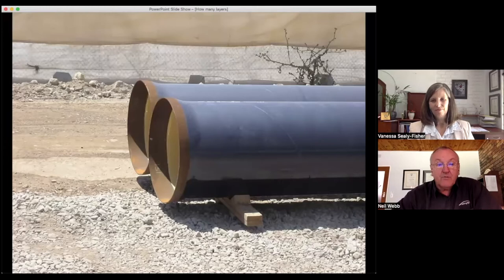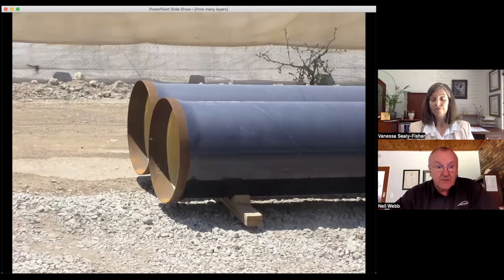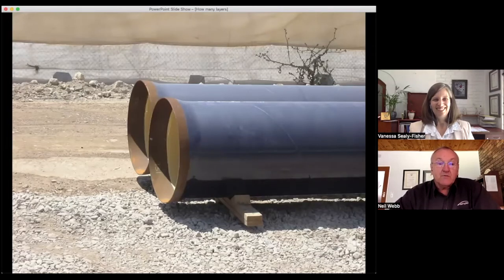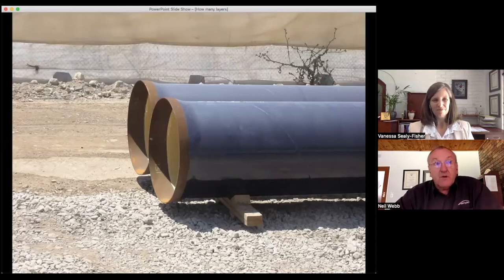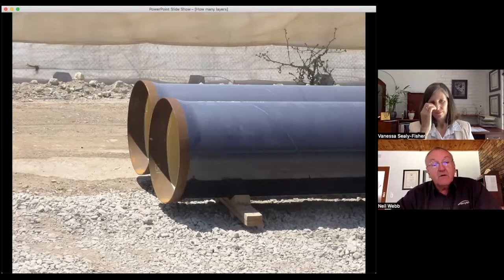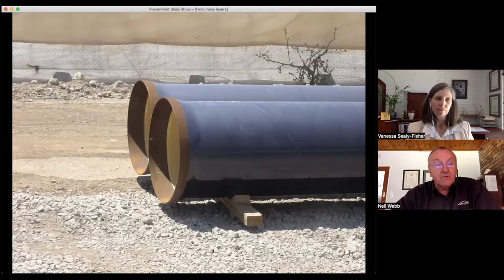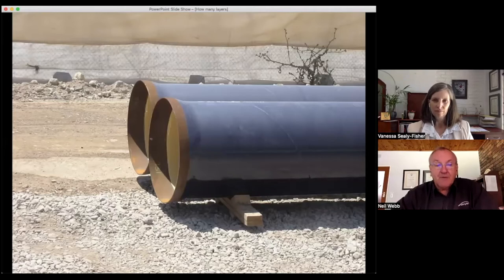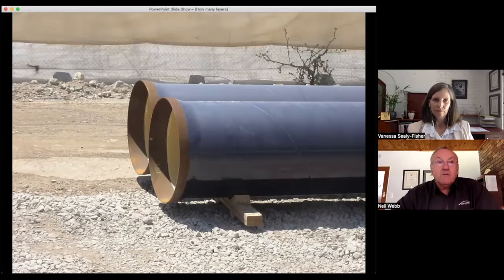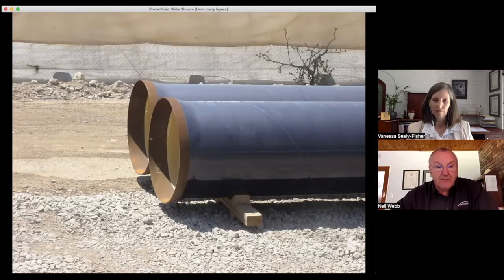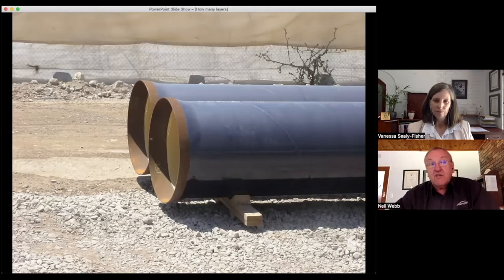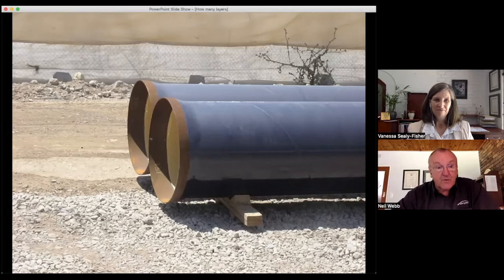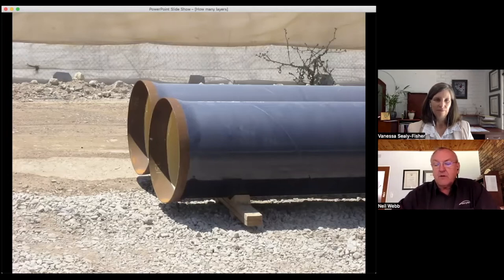Polyurethane foam was used extensively for cast-in-situ field jointing overseas. When they first brought that to South Africa, they injected the foam into the mold and it climbed out and went everywhere because it reacted too fast due to our ambient temperatures. But rigid polyurethanes have now become an accepted and well-documented system in South Africa.